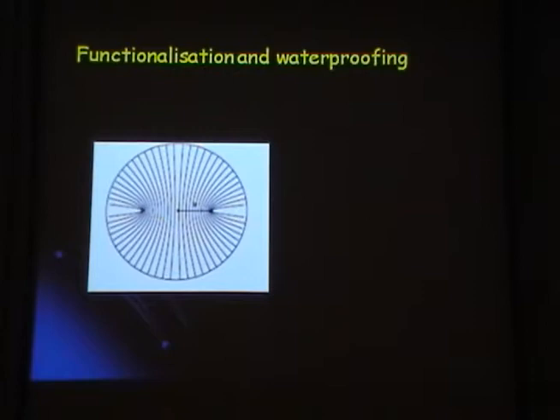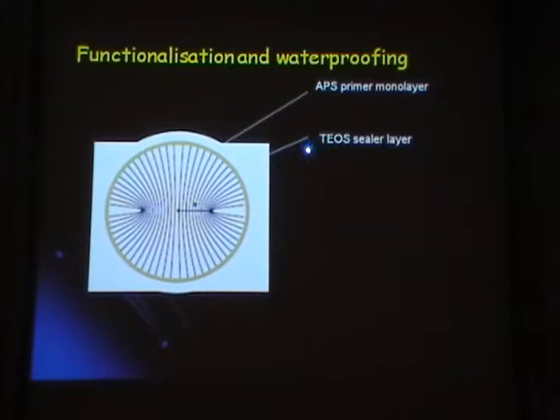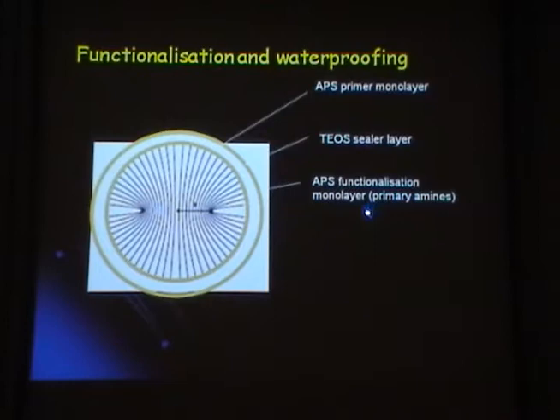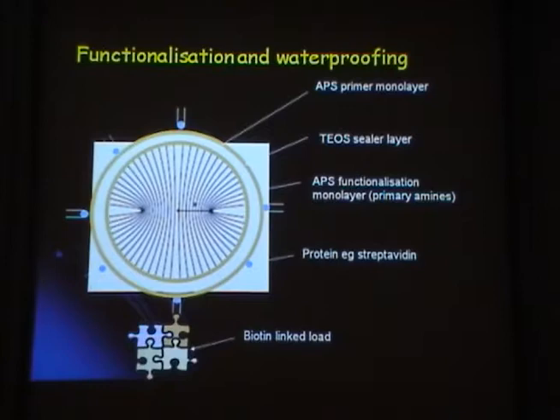which prevents the crystal from melting, and the shell has to be made of such a material that you can also functionalize it with biological proteins. So this is what we do here. We cover the crystal with an APS primer monolayer, and then with a TEOS silica layer, and then an APS functionalization monolayer, and then we put proteins on it, for example, streptavidin, and then we come with biotin and see whether they will bind. If we are able to do all this, then it means that we can use those crystals for some useful stuff rather than just looking at how they rotate, which we like a lot anyway.